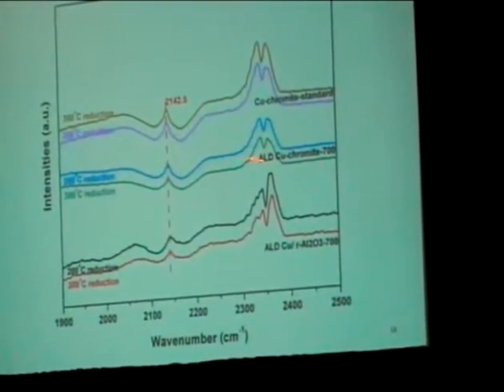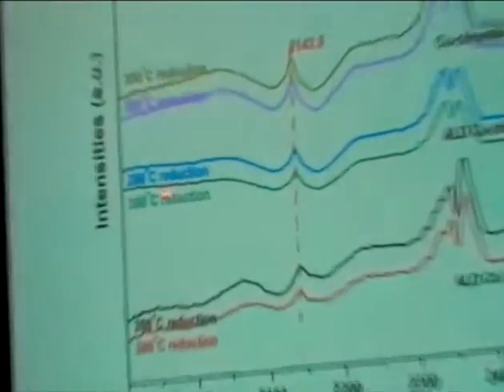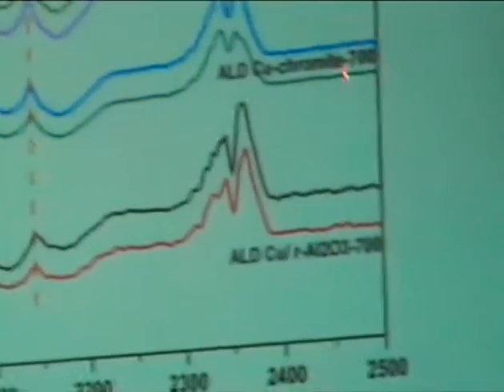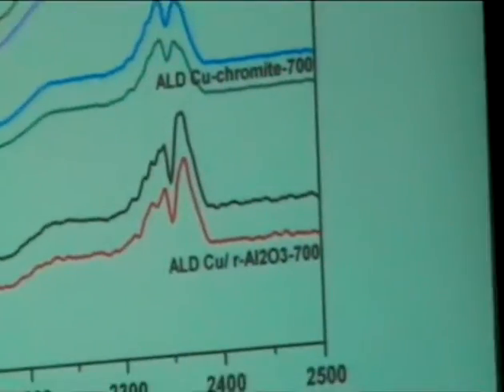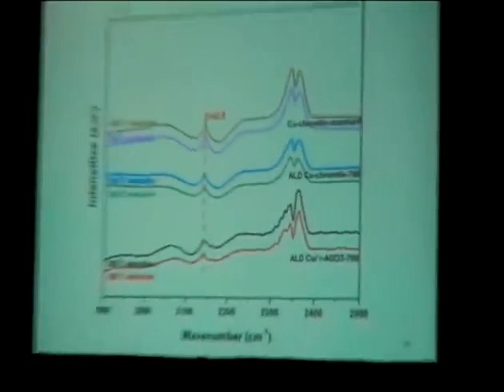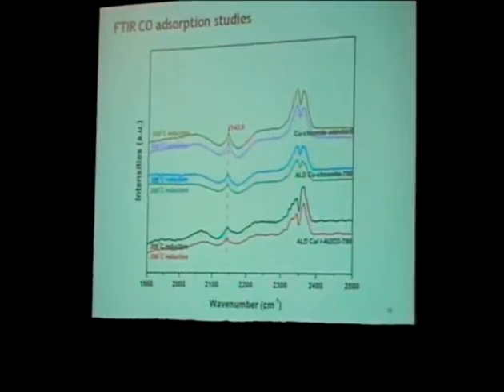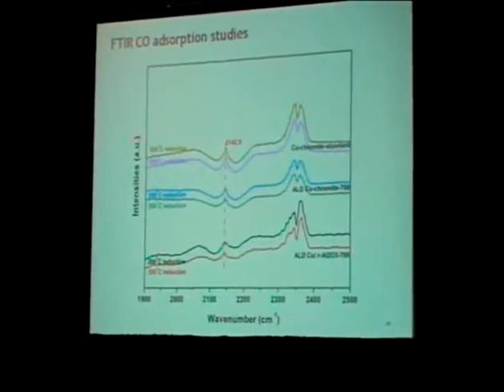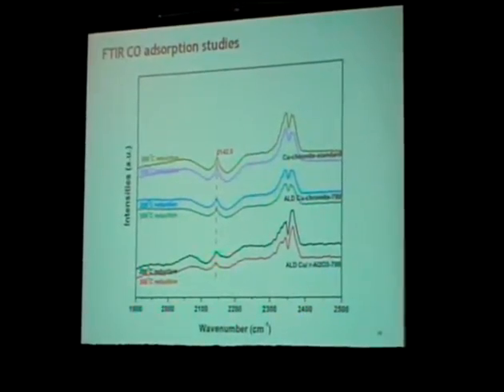Here in the blue and the light green is the ALD coated copper chromite catalyst that has been calcined at 700 degrees. You can see we see the same band showing up here. So basically we have not changed the primary component of this catalyst by doing the overcoating, as shown here by the CO adsorption studies.